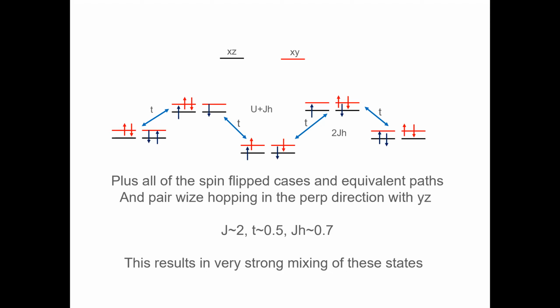And then the strain comes on top of that, orbital ordering comes on top of that. But that's also a very interesting thing. Well, this could also result in orbital ordering, actually, in principle. Yeah, of course. But this is a different channel. Even the easy one, the hydrostatic pressure should be large in this scenario, and that's actually what has been seen. I think that's what I found so interesting about your talk also, this very large strain dependence that you have.